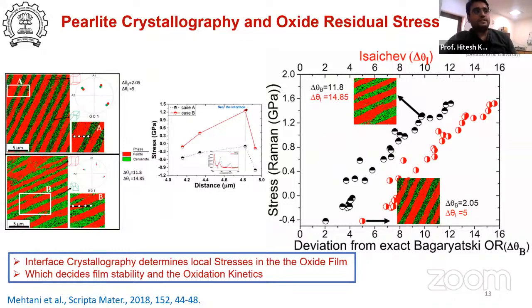As you know, the stresses in the oxide film may lead to cracks, because they are basically compressive or tensile stresses. In this phase, it is tensile stresses forming on the oxide scale. These stresses are providing more pressure on the oxide scale, and it gets cracked. These cracks later provide space for the oxygen to interact more with the substrate, and this part is becoming more oxidation prone.